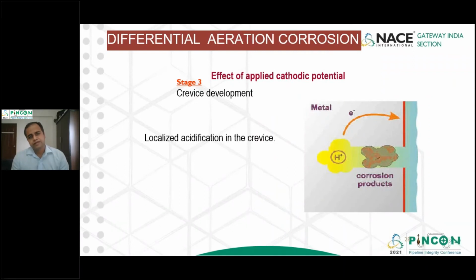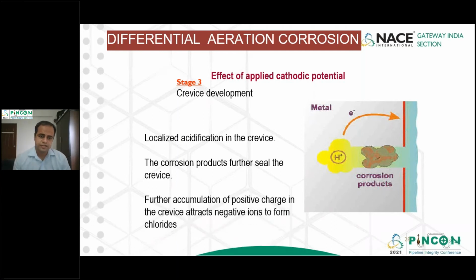Now, when we impact the cathodic potential, we see there is a crevice development which is happening because of the corrosion products which are forming over time because of the polarization phenomena which is taking place outside the holiday and the rusting which is taking place inside the crevice. This is a localized acidification in the crevice. The corrosion products further seal the crevice and you get to see that the accumulation of positive charge in the crevice attracts negative ions to form chlorides.